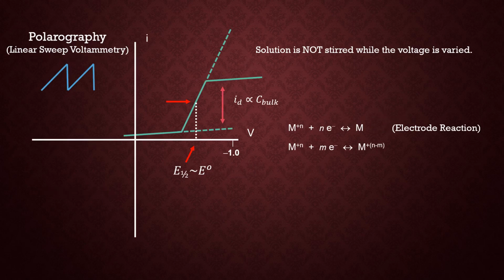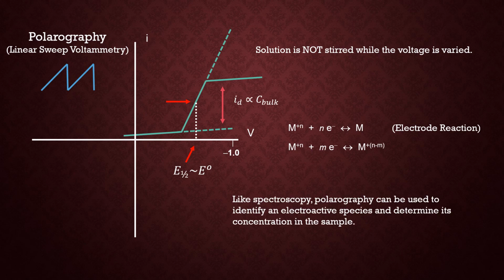So the upshot is I have a polarogram, a current voltage curve, that has two pieces of information. The first is the identity of the material, given by the half-wave potential E1/2, comparing that to the standard tables of redox potentials for metals in solution, and using that to identify the material. Secondly, I can use the magnitude of the diffusion current to tell me the concentration of that electroactive species in solution. So polarography, voltammetry, is essentially like an electrochemical spectroscopy. I can identify the material from the energy relationship, namely the voltage, and how much from the response. Current here is analogous to absorption, whereas the E1/2 is analogous to the wavelength in spectroscopy.